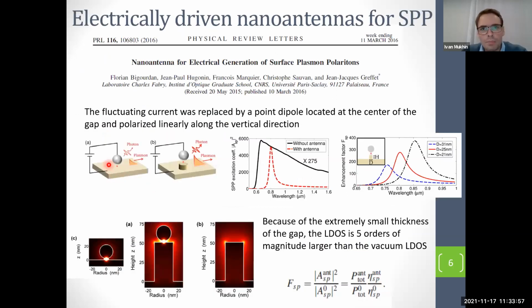So this is a very nice paper published several years ago. The group led by Professor Greffet have shown that if this tunnel gap is considered as a sphere and a metal substrate, and they introduce a gold nano antenna in the shape of a nanodisk in the vicinity of this gap, you can increase the efficiency by 2 to 3 orders of magnitude. And what is also important, by tuning the dimension, the height or diameter of your antenna, you can tune the spectral position of emitted light.